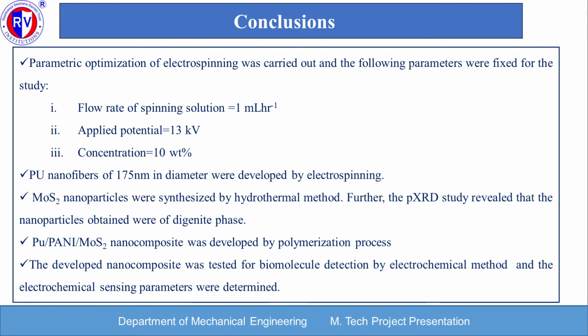MoS2 nanoparticles were synthesized by hydrothermal method. Further, the PXRD study revealed that the nanoparticles obtained were of digenite phase. PU PANI MoS2 nanocomposite was developed by polymerization process. The developed nanocomposite was tested for biomolecule detection by electrochemical method, and the electrochemical sensing parameters were determined.